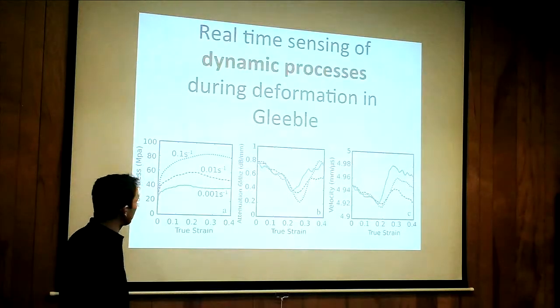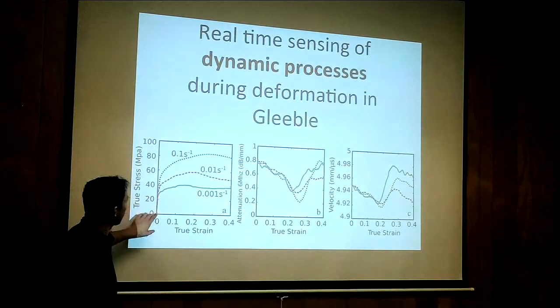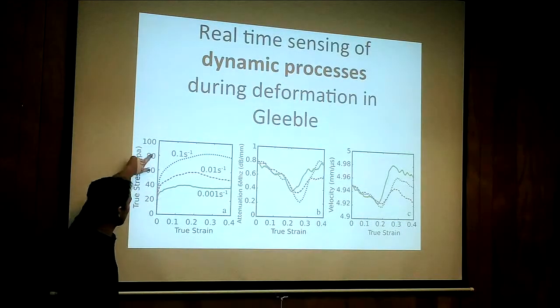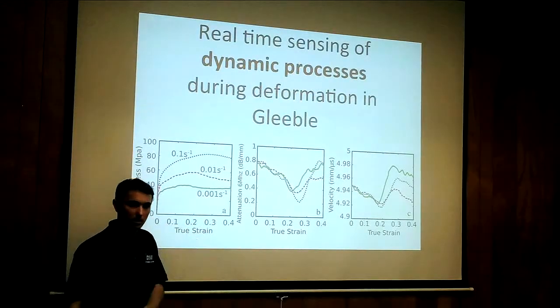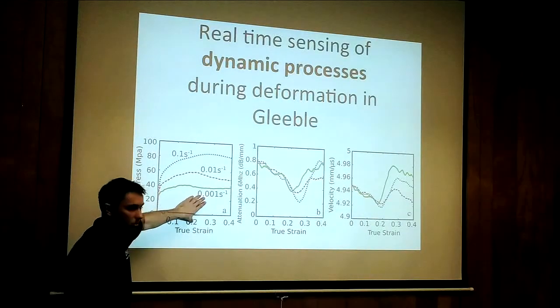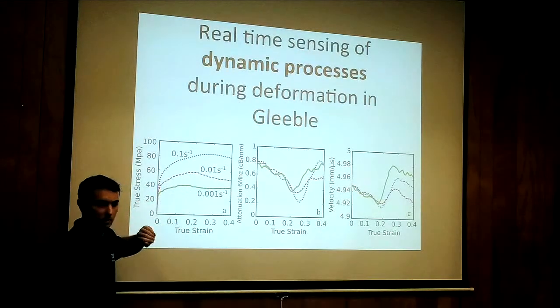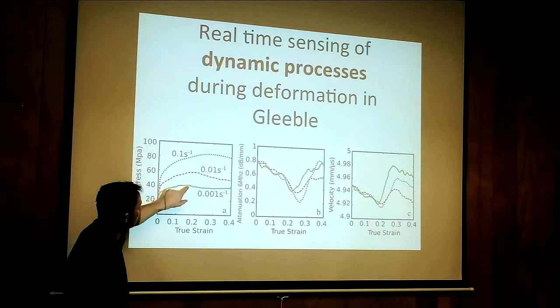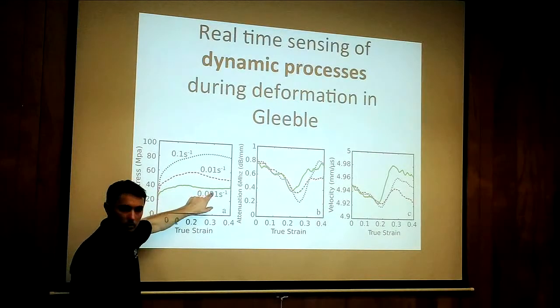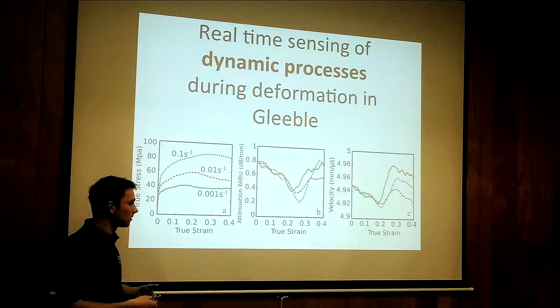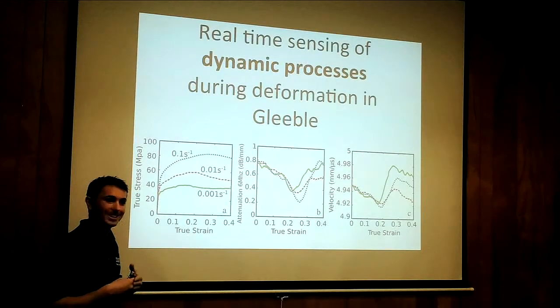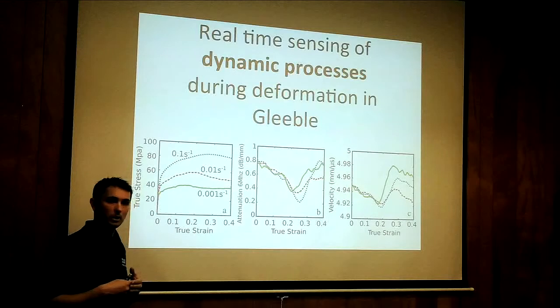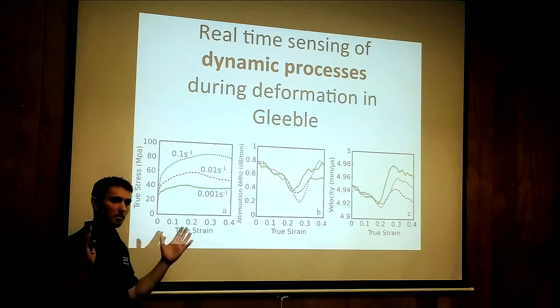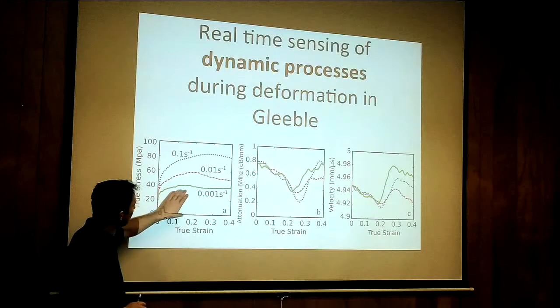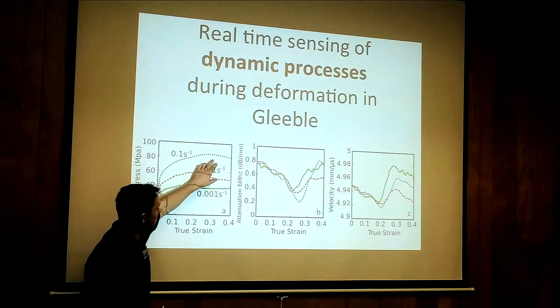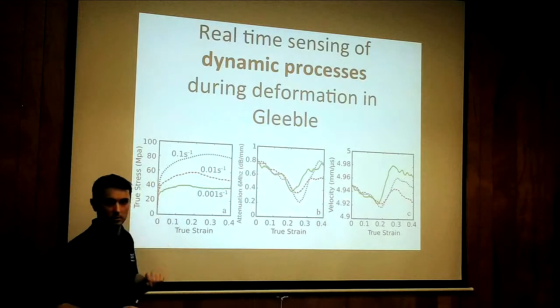And so what we see in this last slide here is first the compression stress flow curve, where we have the stress plotted on the y-axis and the strain on the x-axis. And we have here a very low strain rate and gradually increasing the strain rate. What you see here, there is a broad maxima, and then the flow stress decreases, which is very much associated to a phenomenon called dynamic recrystallization. It's a recrystallization as we saw before, but this time happening during the deformation. And this dynamic recrystallization happened later at higher strain as we increase the strain rate.